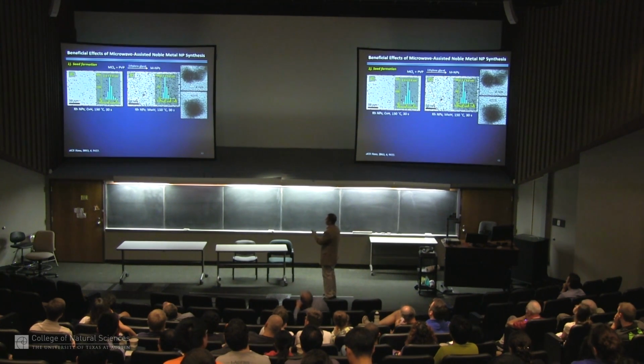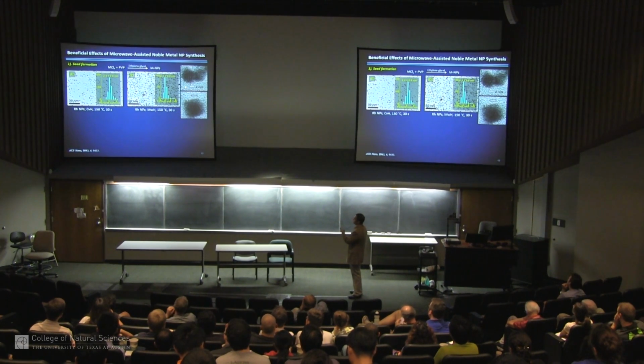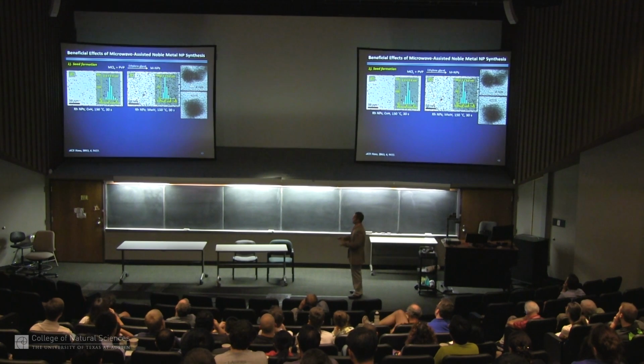If you do the same reaction in exactly the same glassware in the microwave at the same bulk temperature, you see there's a huge difference. We make fewer larger particles. After 30 seconds, they're already highly crystalline. We can see by high-res TEM that they're very ordered. And this tells us that the nucleation and growth occurs very quickly. We make this burst of particles, and we can get better control here.